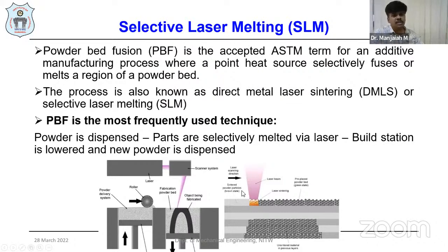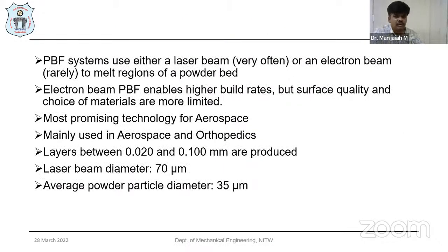These processes are most frequently used for biomedical applications as well as aerospace applications, because it is very fast and gives very good accuracy. It is the most promising technology for aerospace and medical applications, for orthopedics, dental applications, or even implants. In this, we can fabricate layer thicknesses between 0.02 millimeter and 0.1 millimeter. The laser beam diameter is 70 microns in the powder bed fusion process. The powder particles we use are around 15 to 45 microns in size. This is the distribution range of the powder particles we use.